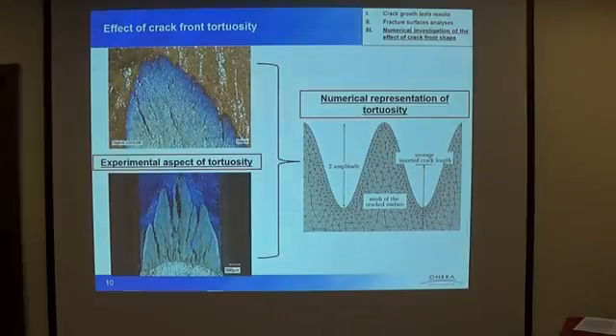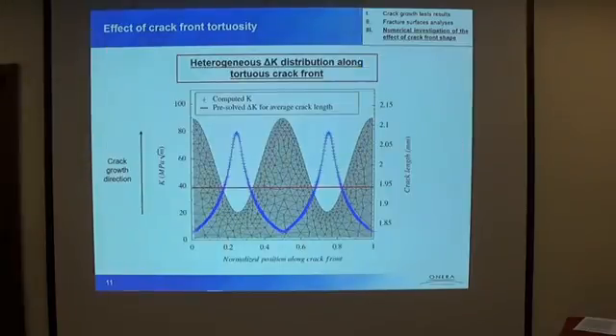Well, let's go one scale further. We decided to investigate the effect of crack tortuosity, since you can see the crack front is all but even. So we decided to represent a tortuous crack front with a sinusoidal crack front in the finite element mesh. Once again, we simulate the crack propagation and apply the DCPD technique.